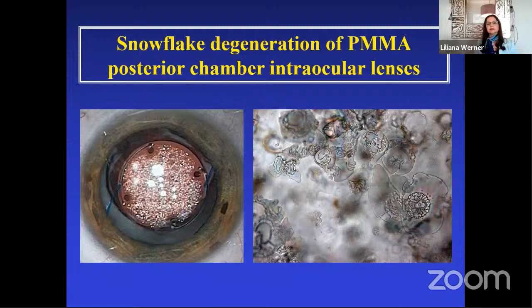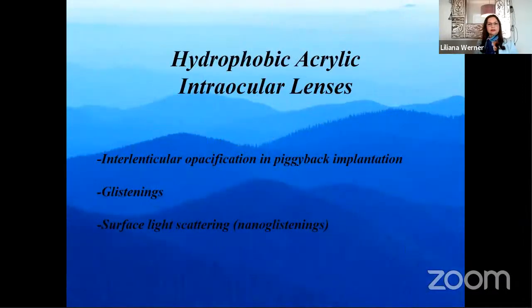Snowflake lesions are usually more concentrated in the central and paracentral areas of the optic of the lenses, because the periphery of the optic is usually covered by the iris, and therefore protected against UV exposure. Snowflake degeneration has not been observed in more modern PMMA lenses, manufactured through other techniques. Regarding hydrophobic acrylic lenses, we will be discussing interlenticular opacification, glistenings, and surface light scattering due to nanoglistenings.